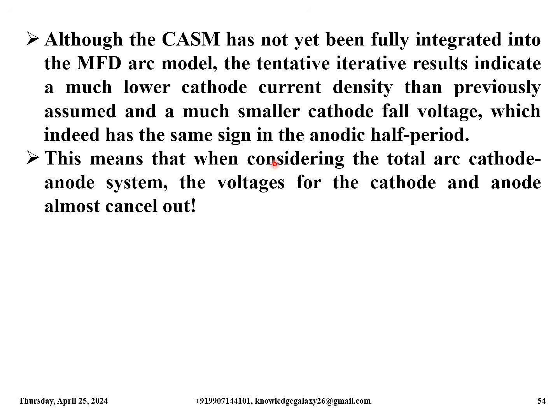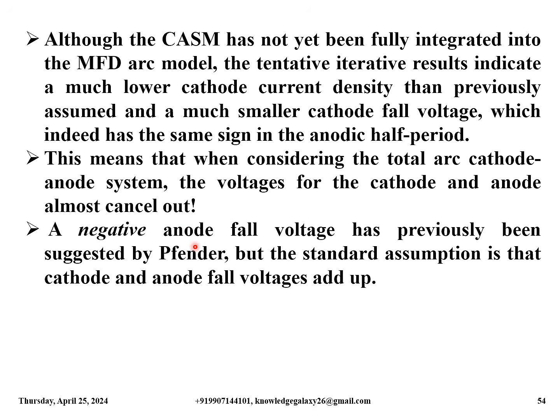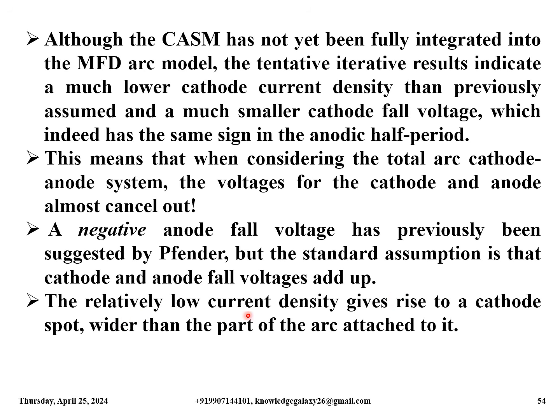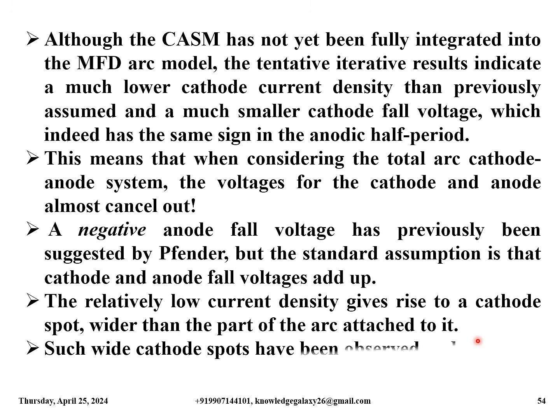This means that when considering the total arc cathode anode system, the voltages for the cathode and anode almost cancel out. A negative anode fall voltage has previously been suggested by Pfender, but the standard assumption is that cathode and anode fall voltages add up. The relatively low current density gives rise to a cathode spot wider than the part of the arc attached to it. Such wide cathode spots have been observed and discussed on some occasions.